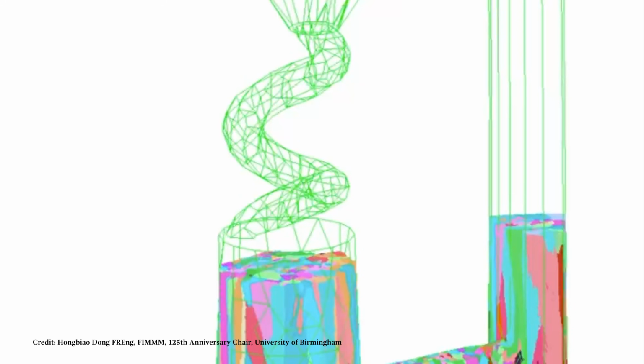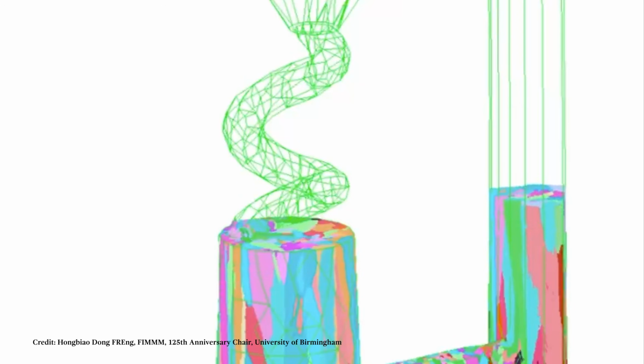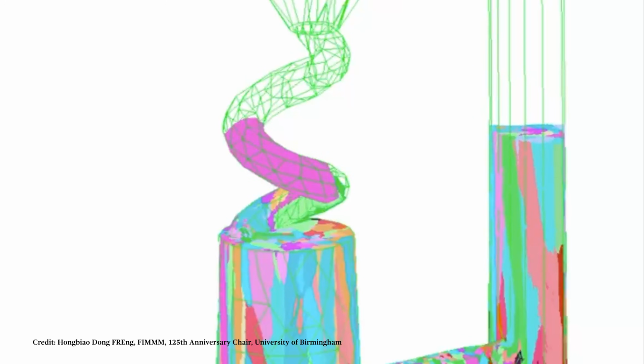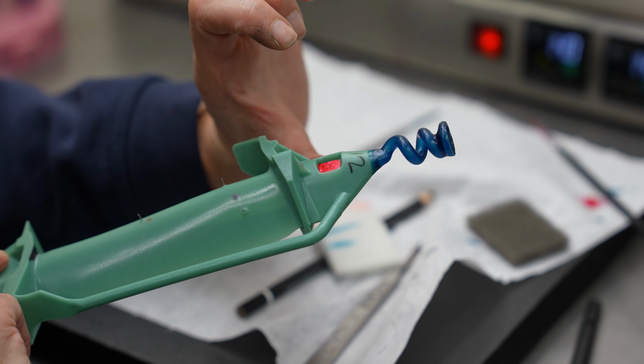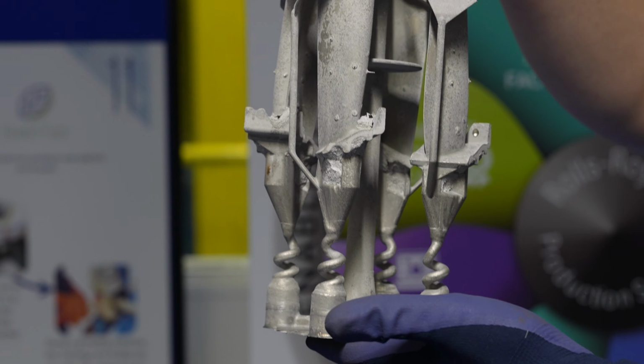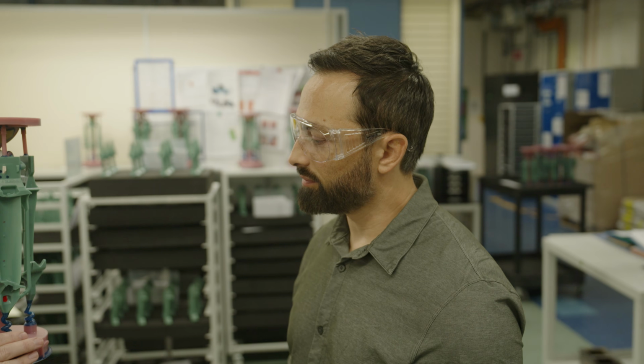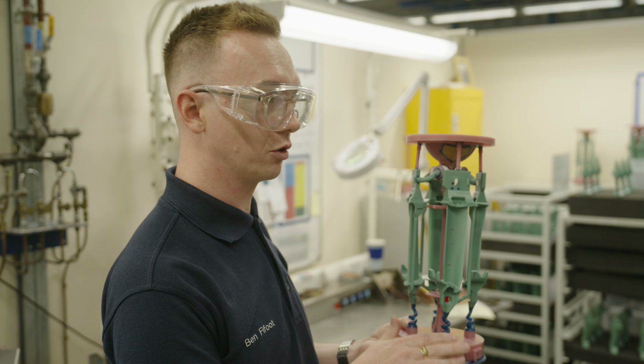If you introduce a bend in the mold just above the chill plate, something strange happens. The number of columnar crystals that make it through drops sharply. And if you add another bend, even fewer survive. So engineers added a helical passage known as the pigtail here at the bottom of the mold. The pigtail is doing the job to select the single crystal.